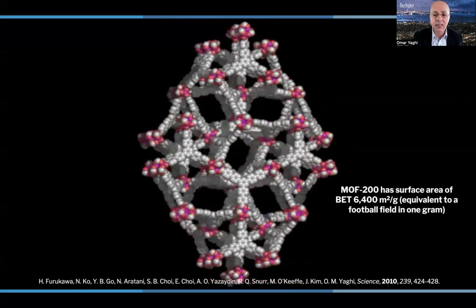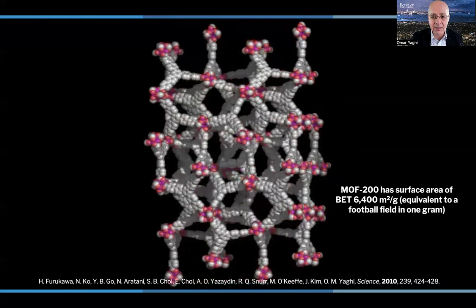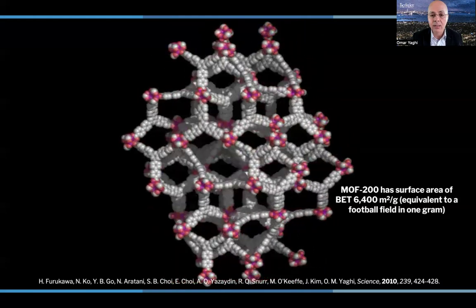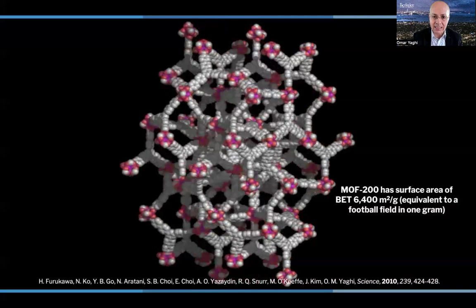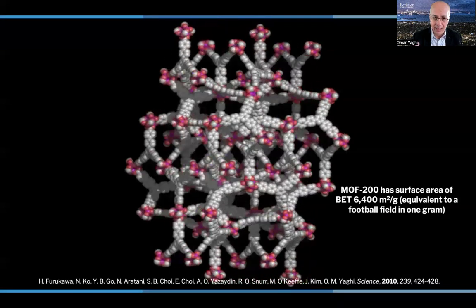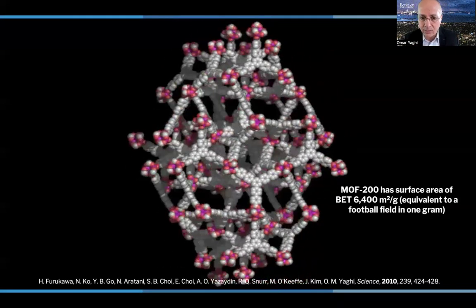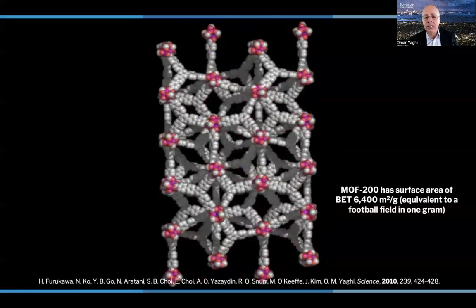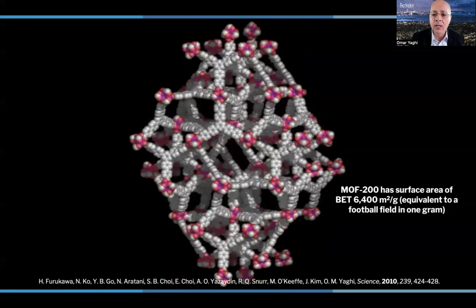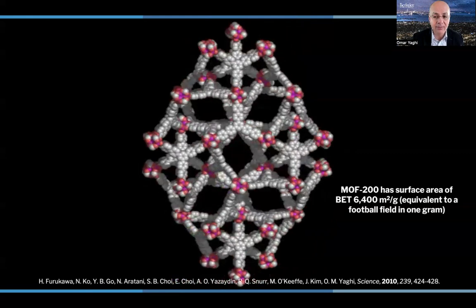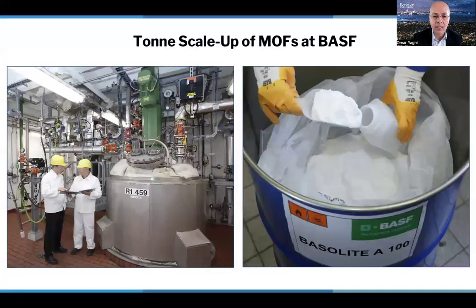Here's a structure that has a surface area of 6,400 meters square per gram. And that's because, as you see, the inside is very open, and you can see it's like a scaffolding onto which gases could be attracted and concentrated. So in 1 gram of material, you have a footage of an entire football field, and that's what makes them special for working with those 4 small molecules that I showed earlier: hydrogen, methane, CO2, and water.